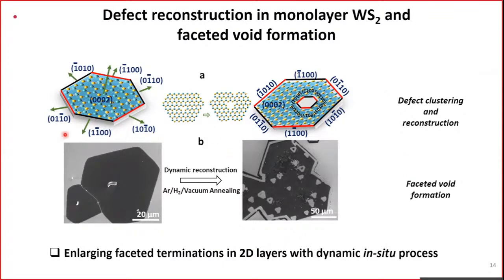What we have done in our group is we first grow the 2D material, typically WS2 in this case. After that, in the process we introduce only 5 minutes or 10 minutes of post-process annealing, typically in argon hydrogen. During the annealing process, as I said earlier, sulfur vacancies can be easily introduced because the sulfur binding energy is much lower compared to the tungsten. Once you remove the sulfur, these point defects can come together and form a void. Essentially, defect clustering and reconstruction result in these nice faceted voids. That is what is shown here.